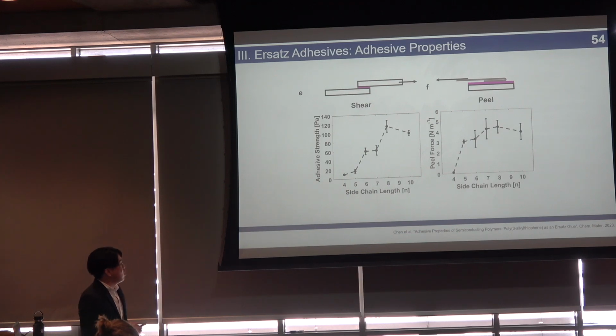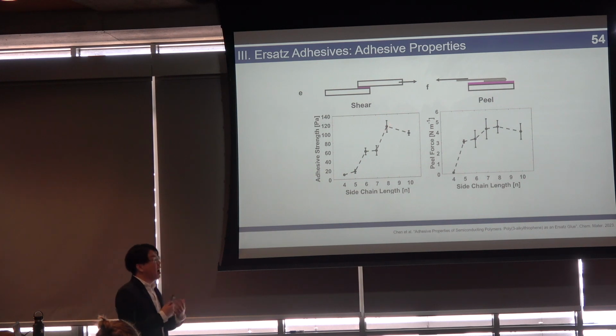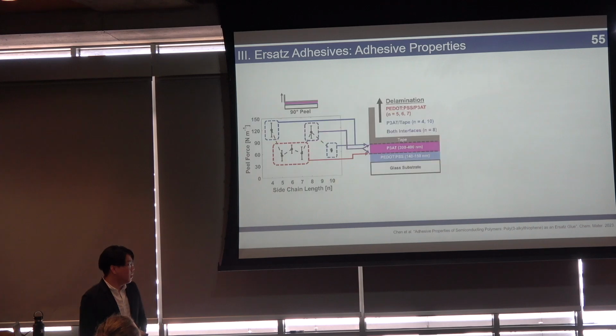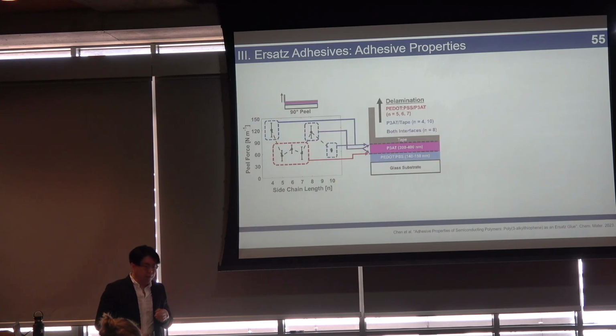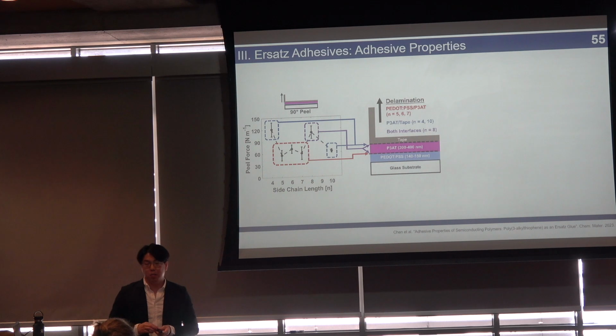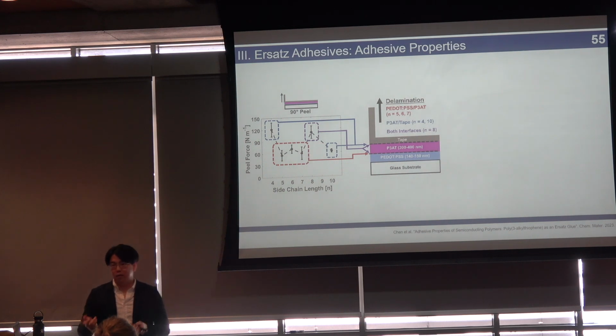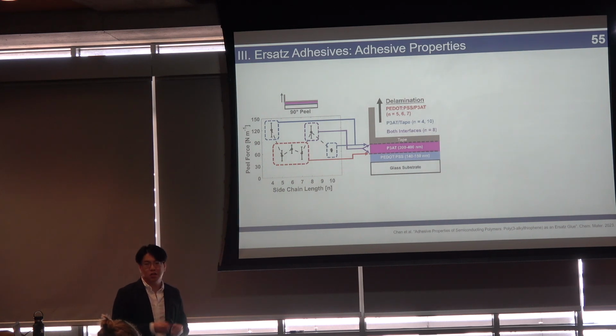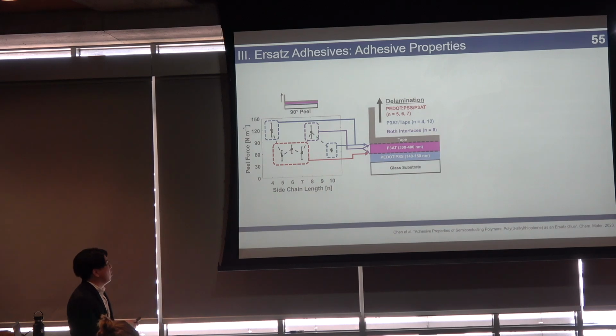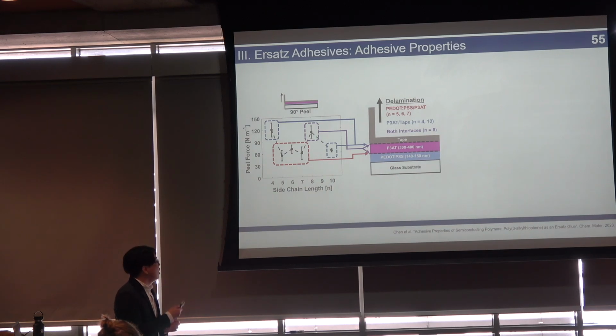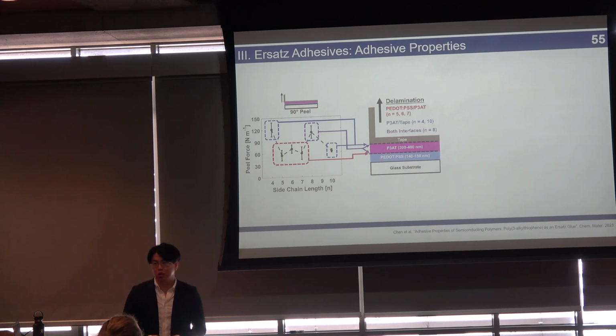And after some normalization, we found that again, the greatest adhesive properties are associated with P3OT, a polymer that has a side chain length n equals 8. Of course, for these semiconducting polymer materials, you aren't ever going to basically put them on a glass slide and just use them as such. As you saw in the previous presentation, we actually have different layers that go below it and above it. So in the case of a solar cell, you might be interfacing with PEDOT:PSS, which is used as a transport